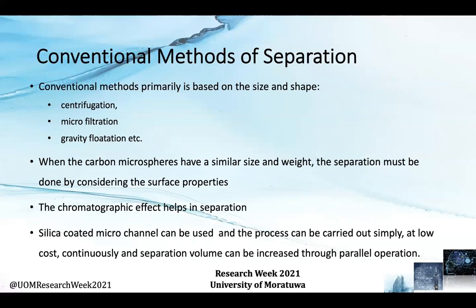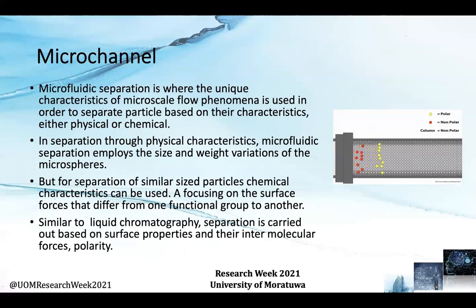Conventional methods such as centrifugation, microfiltration, and gravity flotation are suitable where there is a difference in size and weight of the carbon microspheres formed, but when carbon microspheres do not have such a distinction, separation can be done by considering the surface properties. For this, the effect of chromatography can be used by employing a silica-coated microchannel, and the process can be carried out at low cost continuously with separation volume increased through parallel operation. Microfluidic separation uses unique characteristics of microscale flow phenomena to separate particles based on their physical or chemical characteristics, and in this situation, the chemical separation aspect is what is important.